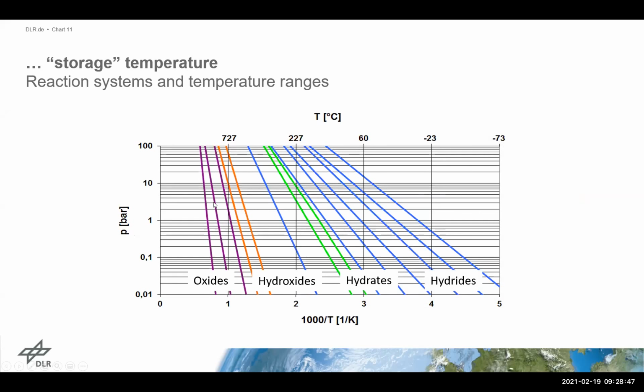We can start at very high temperatures with metal oxides reacting reversibly with oxygen at temperatures above 800 degrees Celsius. And also there, this dependency of the reaction temperature on the gas pressure occurs. So we can have temperature adjustment during the storage operation. We have calcium hydroxide, for instance, or magnesium hydroxide. They differ extremely. Calcium hydroxide is an excellent material for utilizing this, call it advantage.